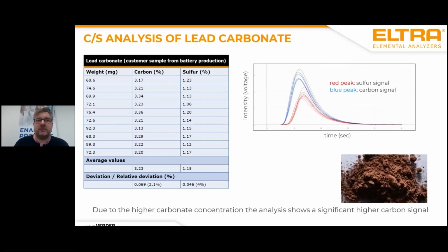The other sample we analyzed was lead carbonate. We also started with carbon sulfur analysis. We also used a sample weight of approximately 70 milligrams up to 90 milligrams. Here we found a carbon concentration of 3.23 and a sulfur concentration of 1.15. Here you also have different colors for carbon and sulfur. The red one means the sulfur signal, the blue one means the carbon signal. And when I have a look at the heterogeneity of the sample, the results are more or less pretty good. And again, it depends on the homogeneity of the sample, how precise this measurement could be.